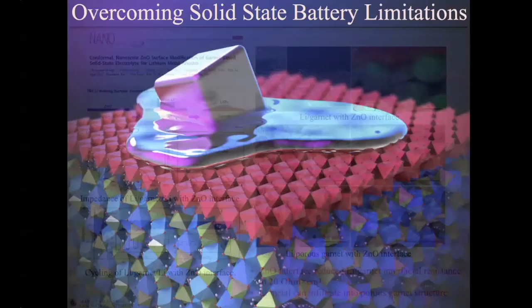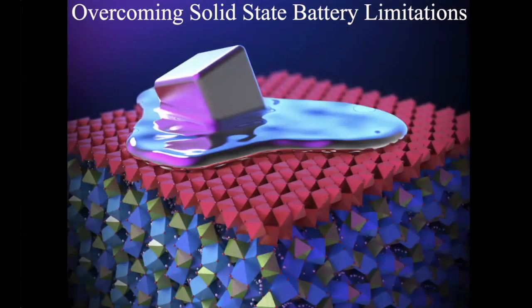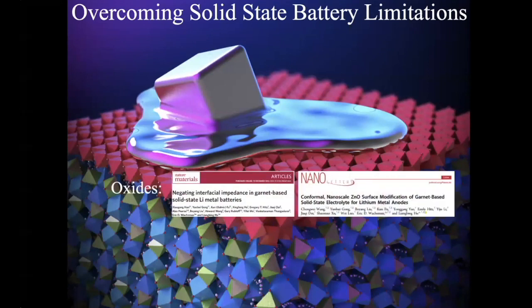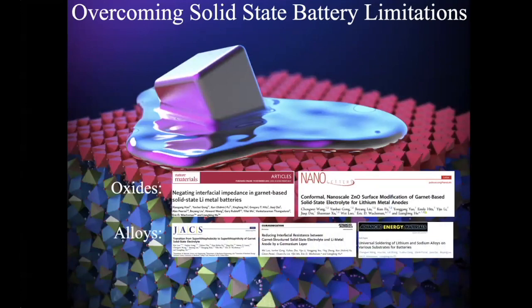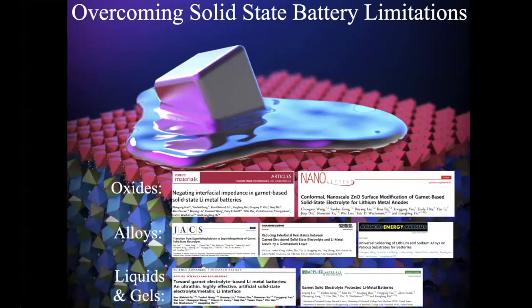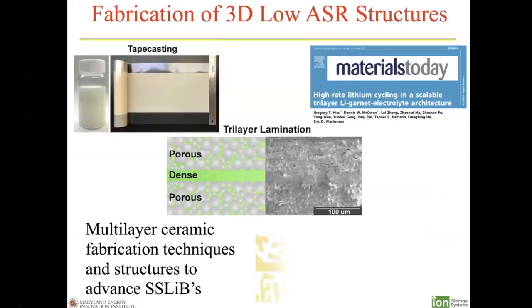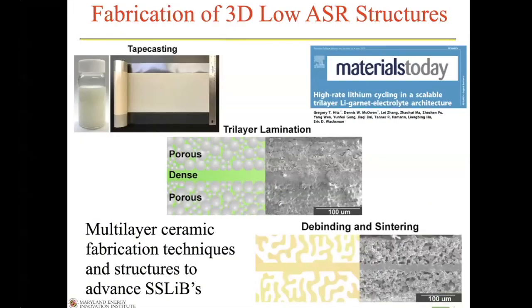So overall, this is a critical thing. Your two solids need to wet each other, and this is the case for lithium metal. We've done this with oxides, alloys, liquids and gels. All of these overcome that intrinsic interfacial impedance by allowing a conformal coating of your electrode material on top of your electrolyte. But the other thing we've done is develop a structure that allows the dense layer in the center to be thin and provides an extended three-dimensional network that gives higher contact area for your electrodes.